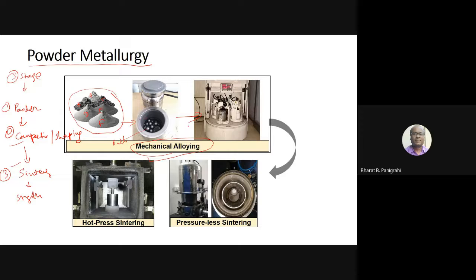So what we have here is the balls, which are typically made of tungsten carbide. The container inside is also made of tungsten carbide. Balls are also made of tungsten carbide. These are the hardest balls and vials available, so that it can crush better. You have balls of steel also, but steel is softer, so it leads to deterioration of the material, ball as well as container. So we typically prefer to use tungsten carbide, which is much harder and much more stable.